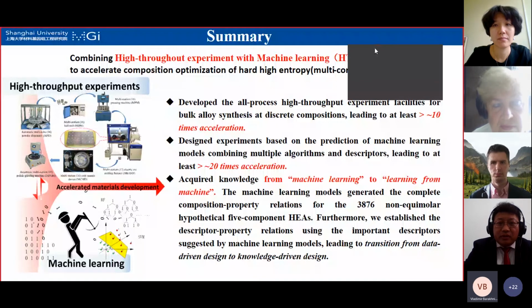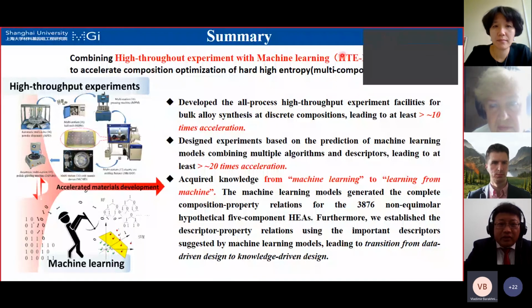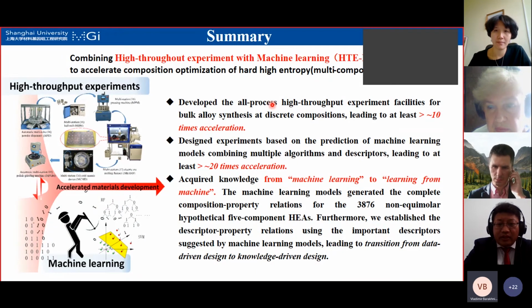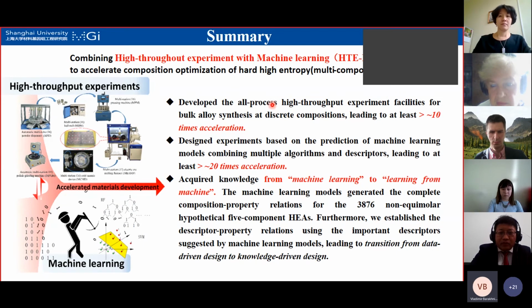So I think this is a summary. We combine high throughput experiment with machine learning to accelerate the composition optimization of high entropy alloys. If we apply the HTE, the high throughput experiment facility, we can accelerate the composition optimization by 10 times, for example. And by machine learning, we do fewer experiments, so in this case we have a 20 times acceleration. If we combine these two, 10 times 20, we can accelerate the composition optimization by 200 times.